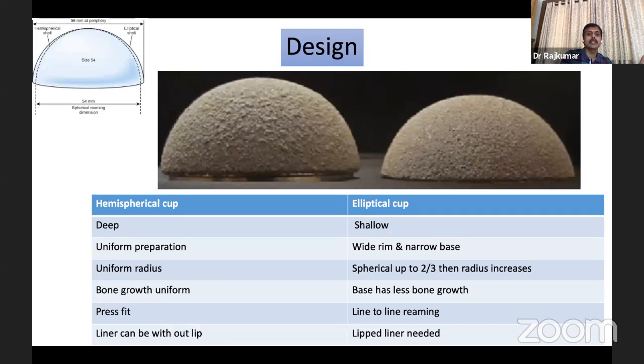If you look at the design, this is the main important design which you have to keep in mind: the hemispherical cup and the elliptical cup. The hemispherical cup is deep and uniform in preparation, and the bone growth is uniform again. The press fit technique is done very nicely in these hemispherical cups. Whereas an elliptical cup is very shallow and the base has less bone growth, so line to line reaming has to be done in these elliptical cups.